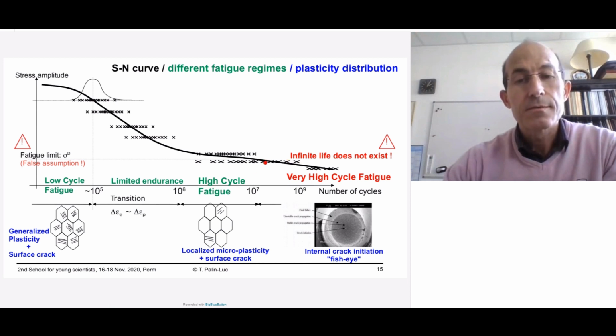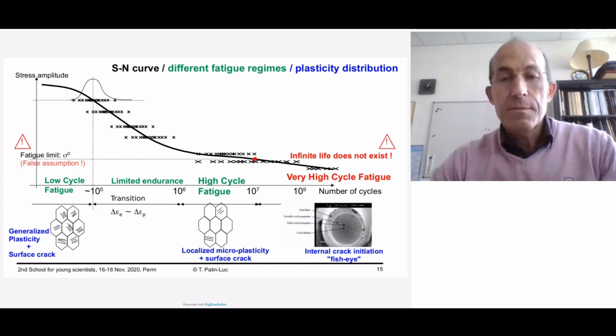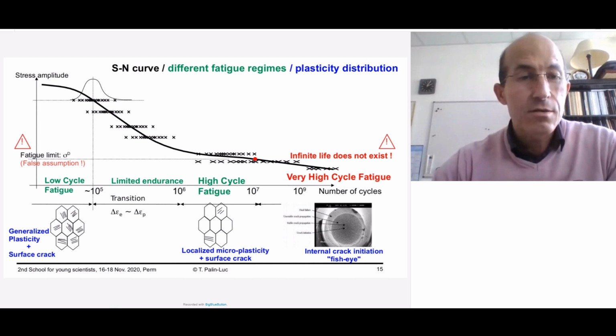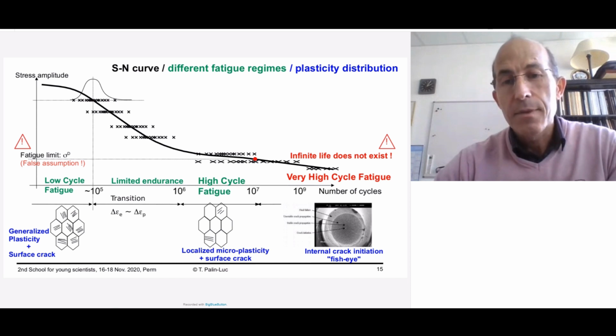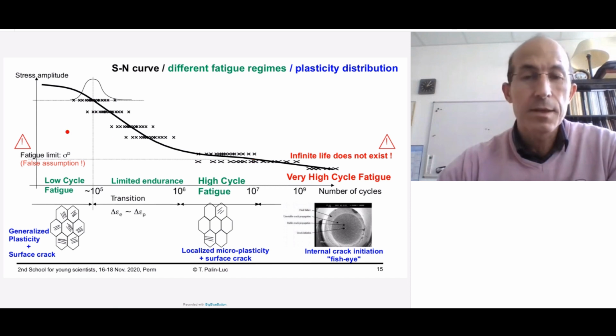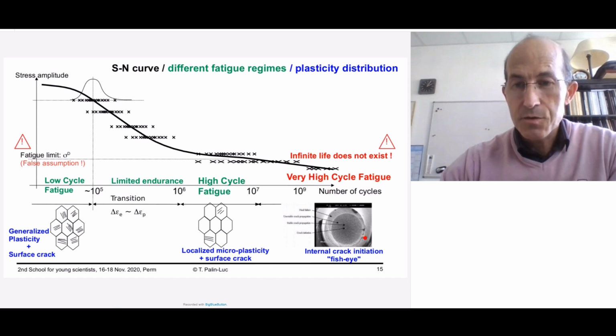Now, if you do not stop a test after 10 million cycles with a non-broken specimen, if you continue, what do you observe? Such experiments have been carried out since the end of the last century by many researchers in Japan, in Germany, especially in France and in the US, and they are named the gigacycle regime or the very high cycle fatigue regime. It has been demonstrated that in this case, infinite life doesn't exist. It means the assumption made by Wöhler about a fatigue limit was false. In fact, if you continue the test up to 10 to the 9 or 10 to the 10 cycles, the material exhibits mainly internal crack initiation with the famous feature named fish eye.